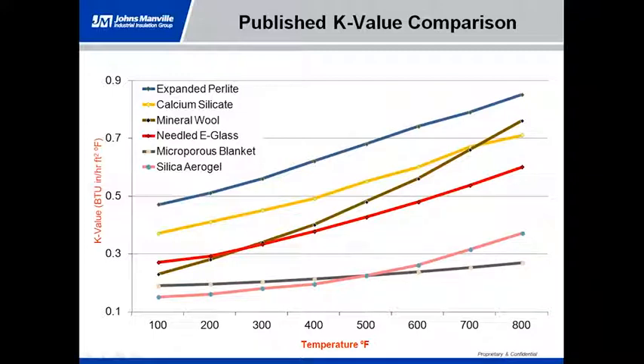Now, in all cases, note that as you go from a lower temperature of 100 degrees up to 800 degrees, the thermal conductivity goes up, which means the rate that heat flows through the material also goes up. This is largely a component of radiative heat transfer.